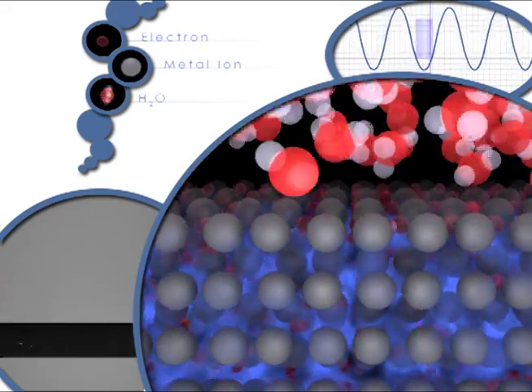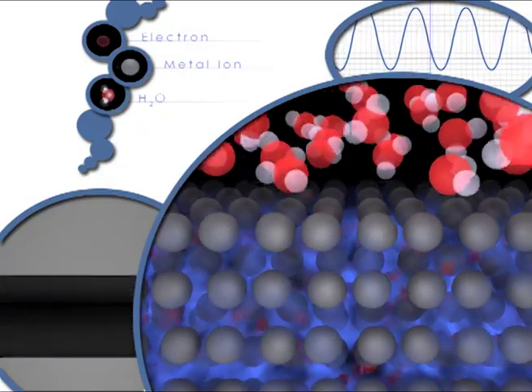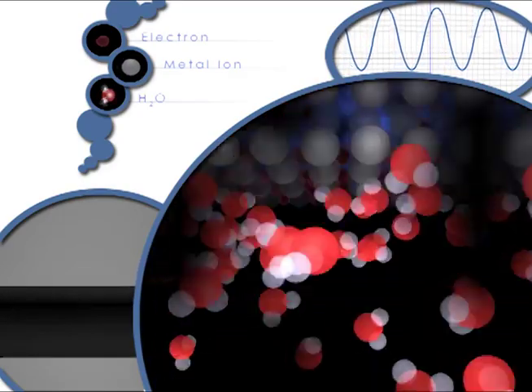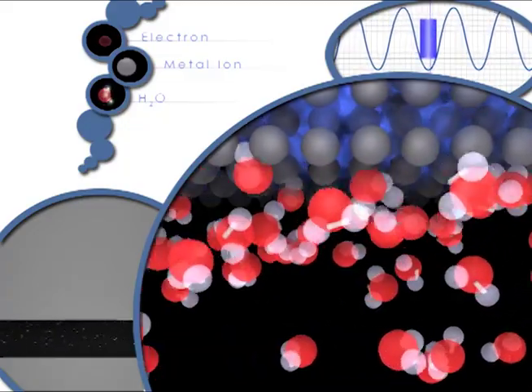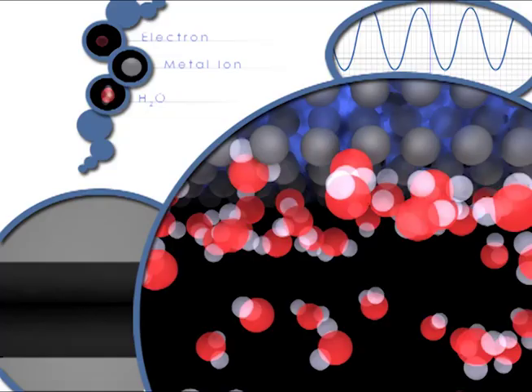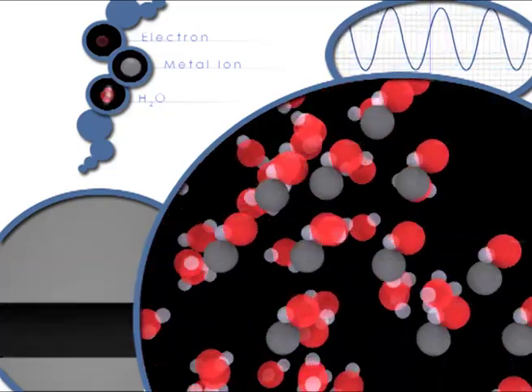In the process gap, which locally is smaller than 10 micrometers, the metal on the anode, or the workpiece, will dissolve quickly and accurately. The released electrons will be used at the cathode for the corresponding reaction. This corresponding reaction may consist of splitting water into hydrogen gas and hydroxyl ions. The dissolved metal ions can combine with these hydroxyl ions to form metal hydroxide.